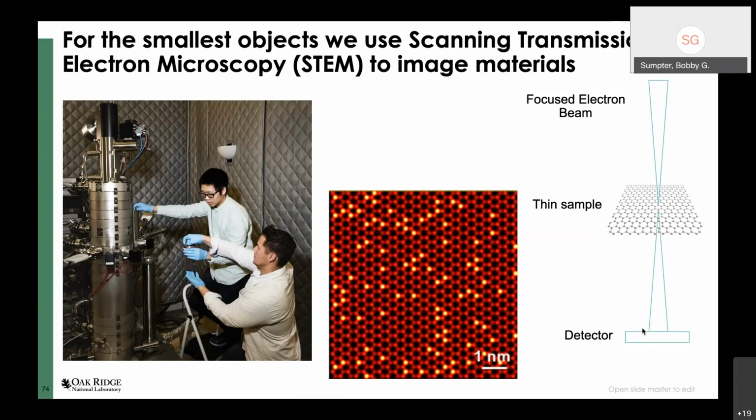So you can see here in the middle that the carbon atoms are shown a little lighter or darker, and these dopant atoms, which are tungsten, it turns out, are shown a little brighter, and that's because this has Z contrast, where Z is the element number, and the brightness increases with it. So the brighter atoms will be the heavier atoms, and the darker atoms will be the lighter atoms.